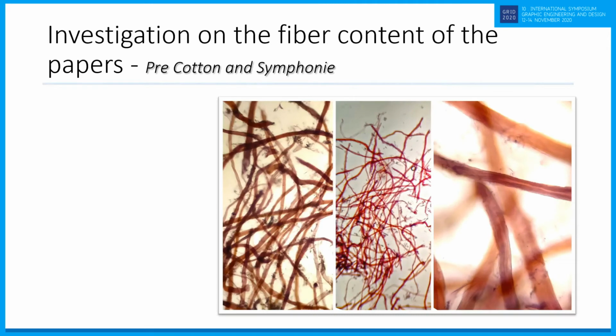The first part of our investigations was focused on the fiber content of the examined papers. The first figure shows the microscopic analysis of pure cotton paper. It is visible that this type of paper consists of 100% natural cotton fibers, which under the chlorine zinc iodine indicator are stained in pale to intensive pink-red color and have the typical natural cotton morphology.